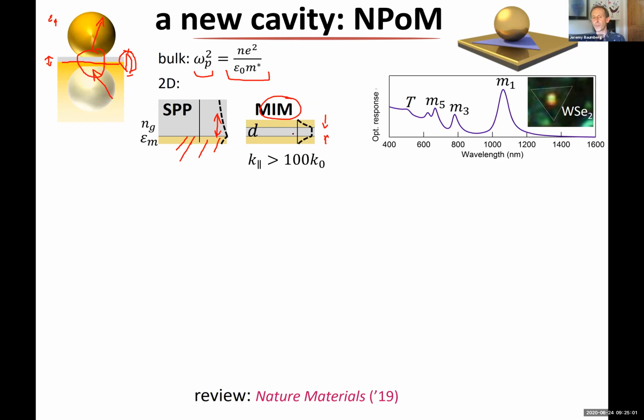There's a mode which really likes to sit in the gap there. The only difference is it starts to go very slowly. So it travels in this direction very slowly, and that's why this in-plane wave vector now becomes much, much larger than the free space wave vector. Essentially, that means that it's traveling at 100 times slower than the speed of light. So this mode here, which you can just solve very easily, sits inside this metal insulator metal gap.